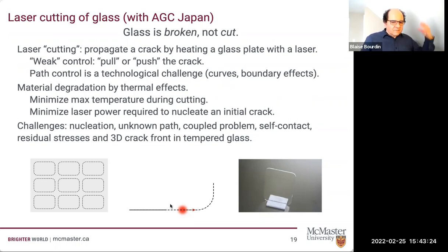And what the glass industry is trying to do is to use a laser beam. And the idea is to shine a laser beam along the crack path. The laser beam causes thermal expansion ahead of the crack or behind the crack tip. And this will, in turn, either pull or push the crack. They have demonstrations of this, but it's really hard to control the path. There's a weak pinning between the laser beam and the crack, so it's not clear that the crack will exactly follow the beam, or sometimes it may deviate and so on.